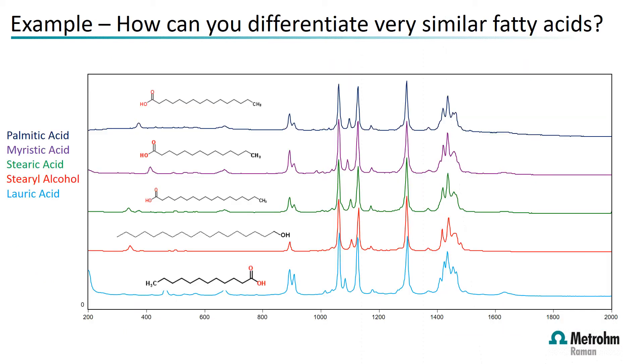Here we look at differentiating very similar materials — a selection of organic acids with very subtle changes in structure, both in chain length and in functional groups. Using a simple peak-picking algorithm, these materials are extremely similar and can produce false positives and false negatives. We have developed a technique that looks at very subtle changes in the spectra — minor differences around 900 wavenumbers and subtle differences in peak shapes around 1500 wavenumbers.